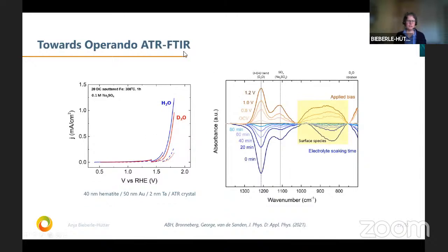Here we see now that we were able to measure on these ATR crystals, that we were able to find a processing way to make low temperature deposited iron oxide with some reasonable performance. And what we did is we measured the infrared spectrum. It's a complicated plot, so mainly we show two measurements here. The one measurement is the ATR-FTIR spectrum as a function of the electrolyte soaking time, because we realized that the electrolyte is soaking into the structure. The reason is that the films were a bit porous.